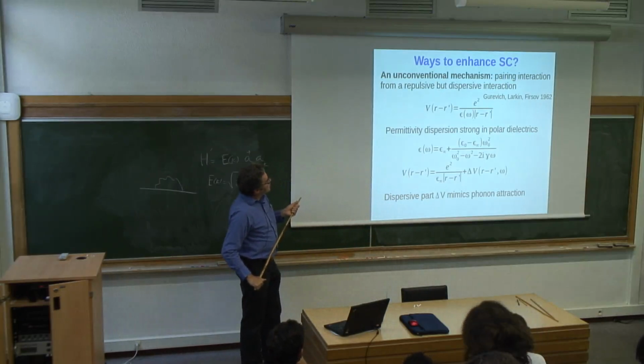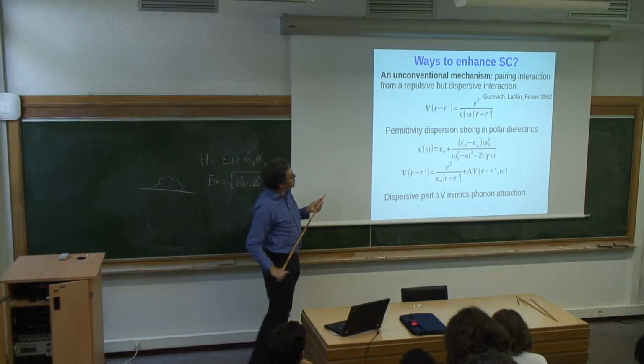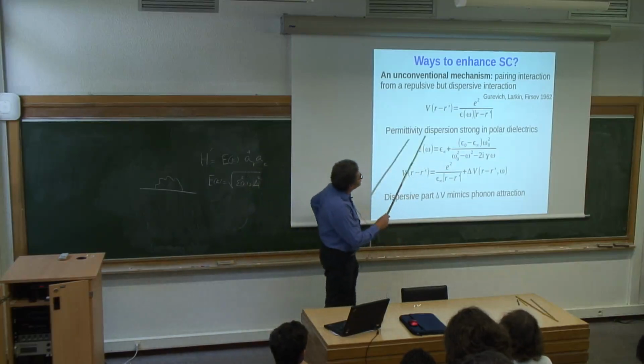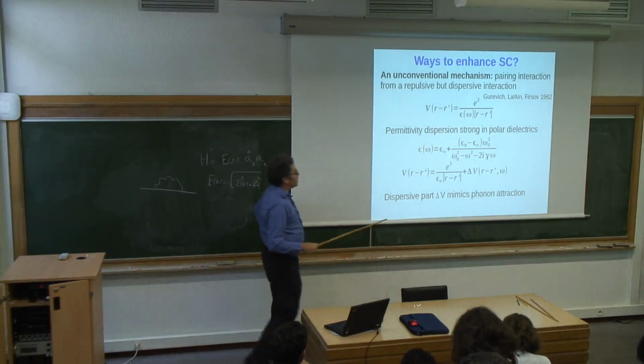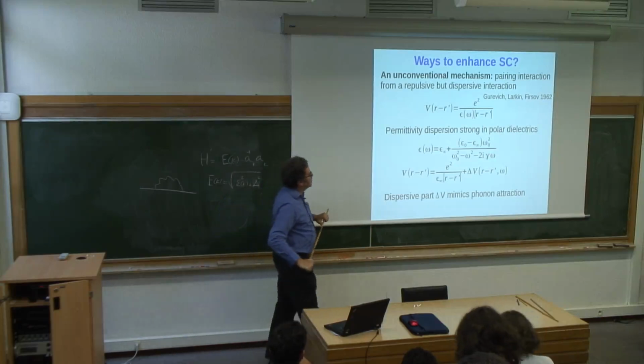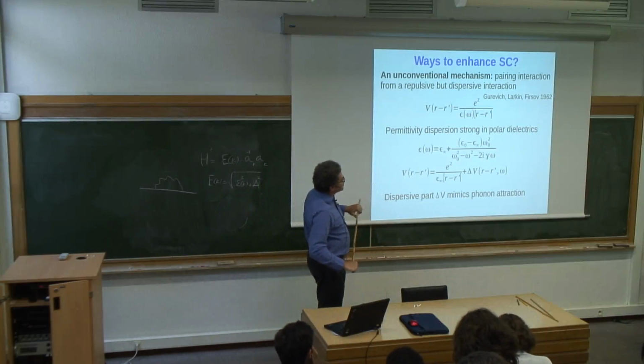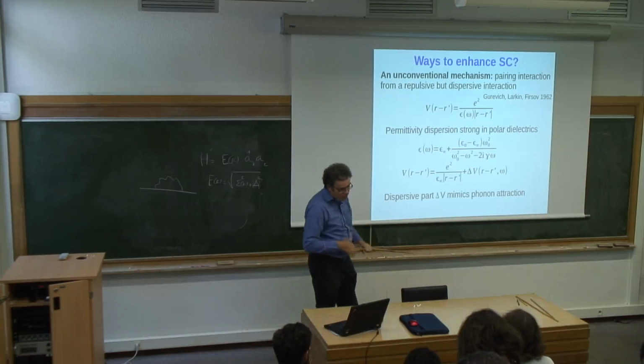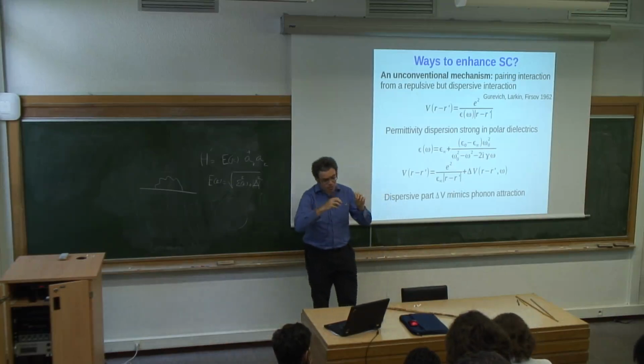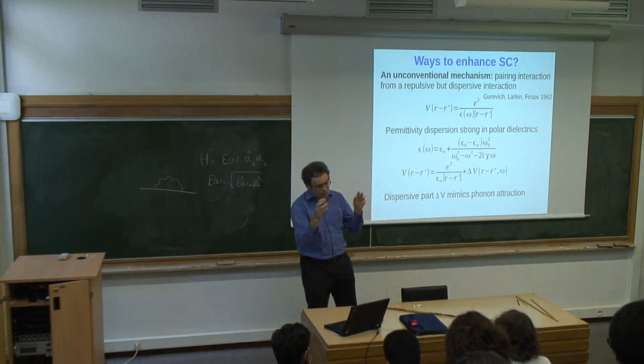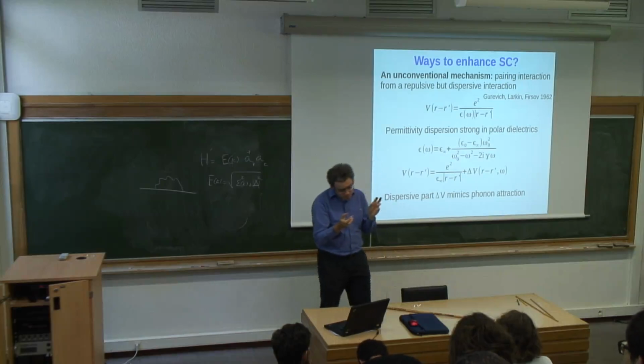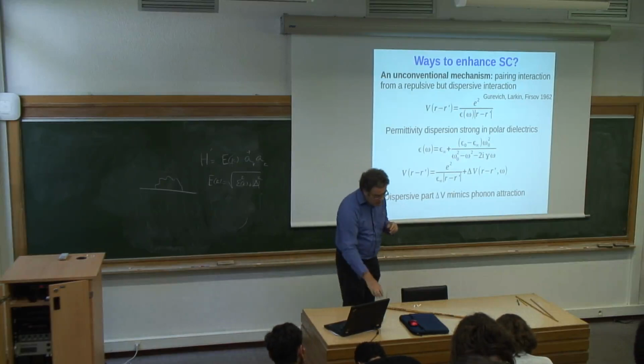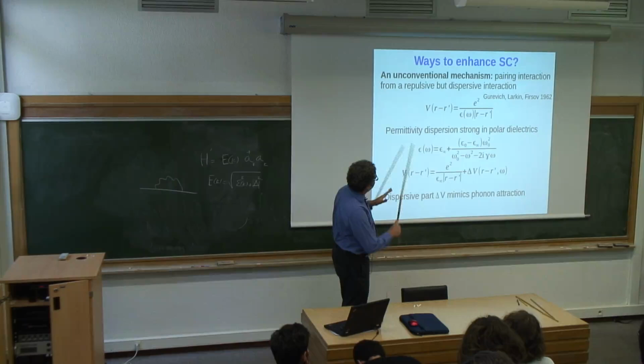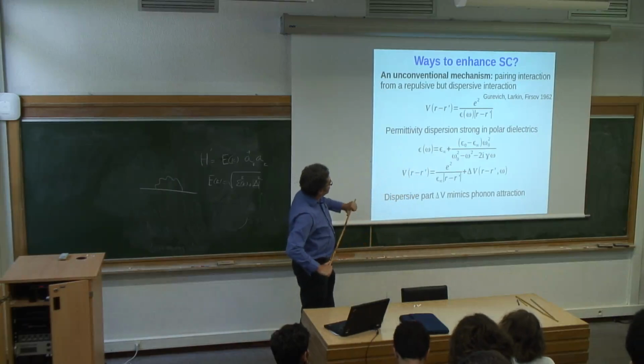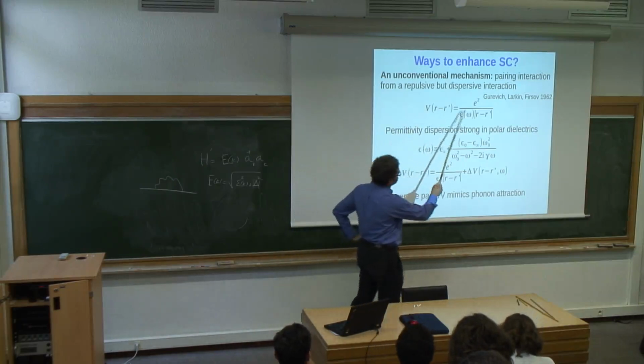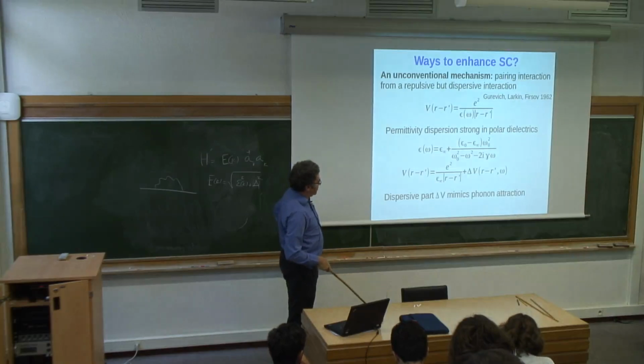So let's suppose that the main interaction is repulsion, and it's Coulomb repulsion. However, the permittivity, that dielectric constant that enters this repulsion, has a strong frequency dependence, and this is always the case in materials. This dependence can be particularly strong in polar dielectrics, where you have different ion species in the crystal lattice, and then they can vibrate in antiphase relative to each other, and this polarization will produce electric fields and will screen Coulomb interaction and will contribute to permittivity. So if you have a metal which has a polar structure, then you have a repulsion, but this repulsion will have this very dispersive character.